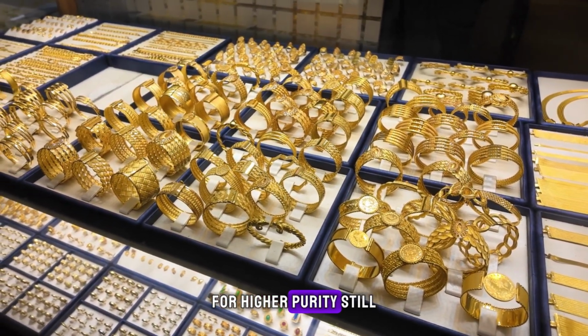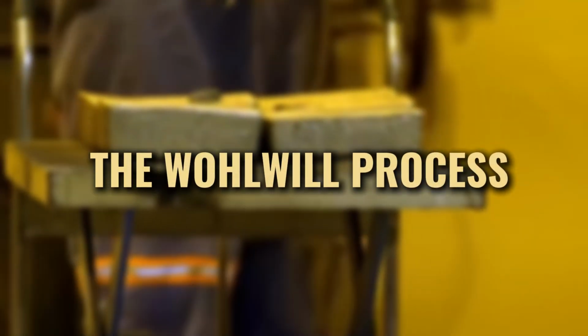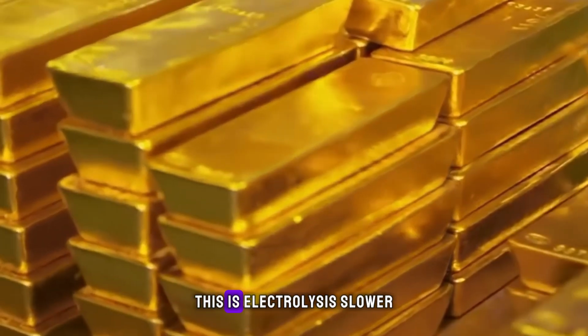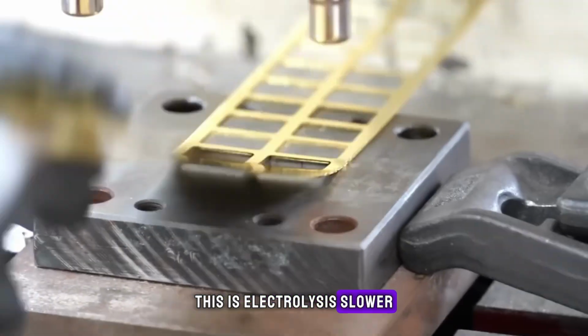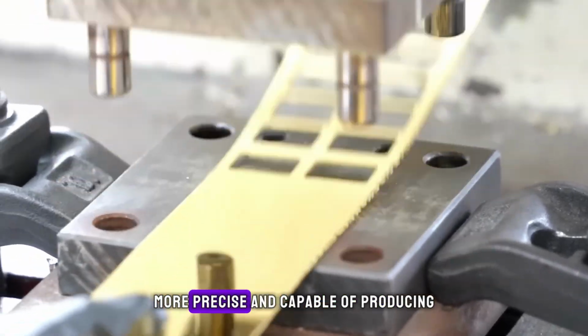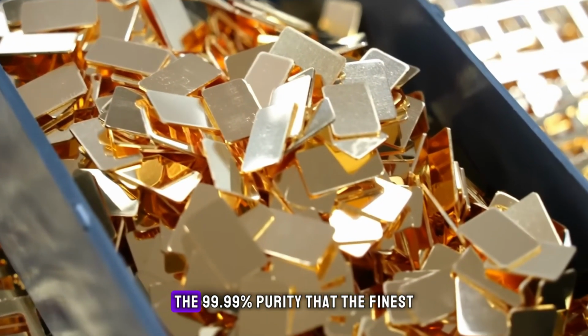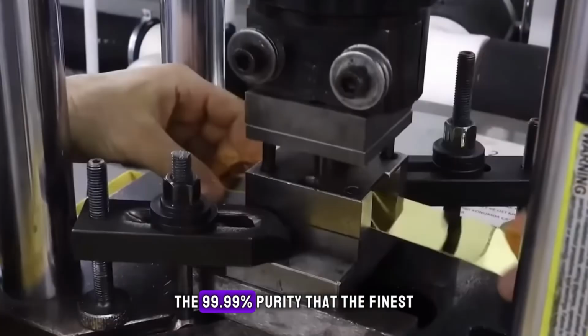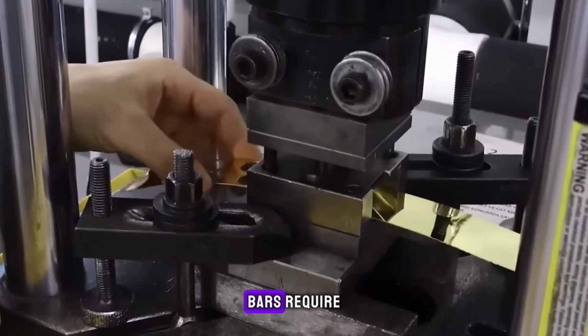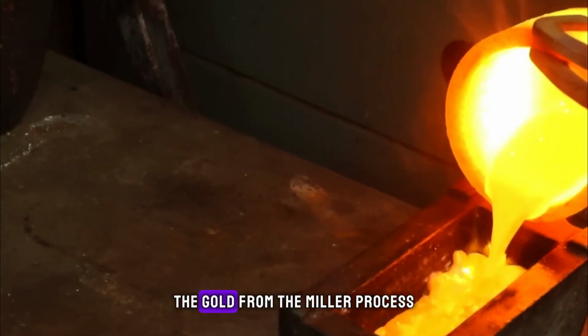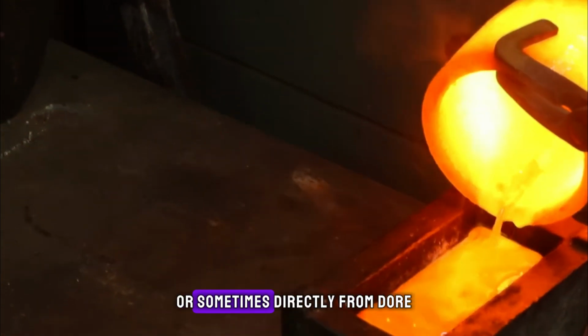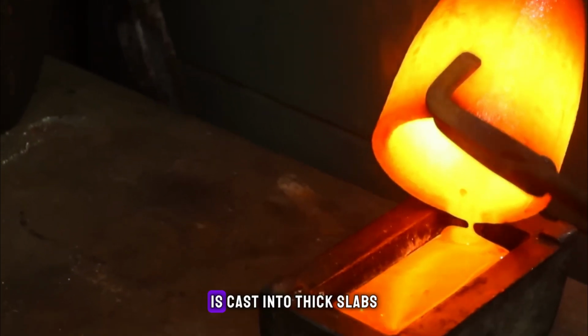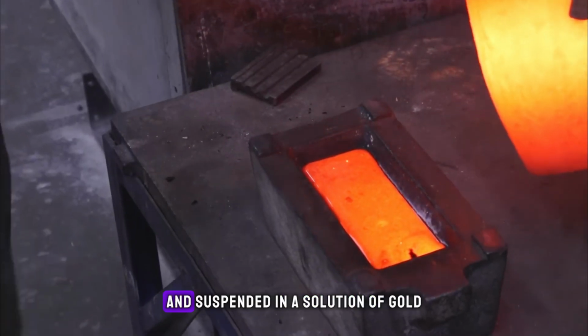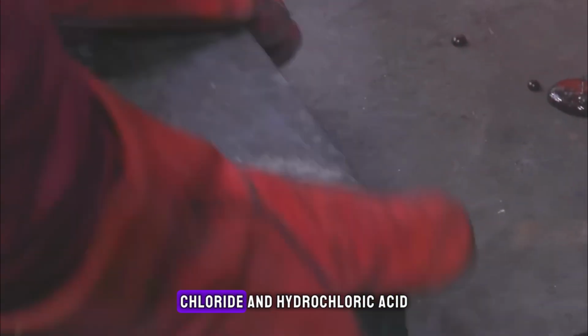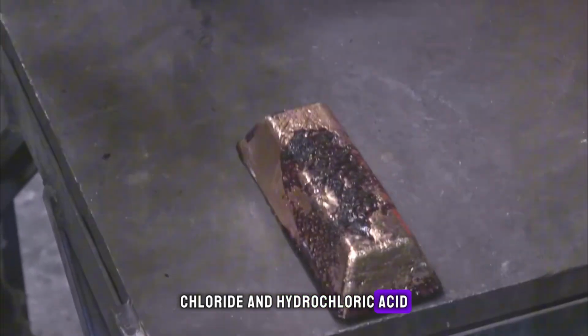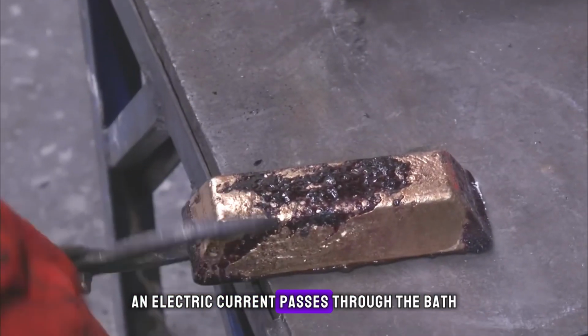For higher purity still, the Wohlwill process takes over. This is electrolysis. Slower, more precise, and capable of producing the 99.99% purity that the finest bars require. The gold from the Miller process, or sometimes directly from doré, is cast into thick slabs and suspended in a solution of gold chloride and hydrochloric acid. An electric current passes through the bath.